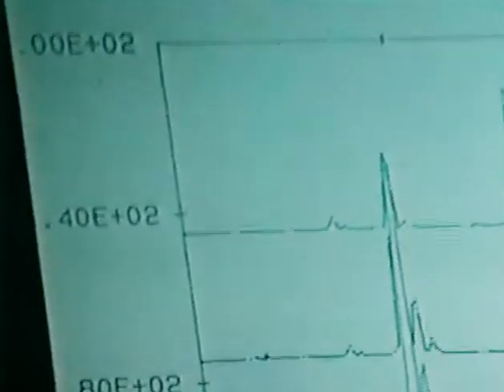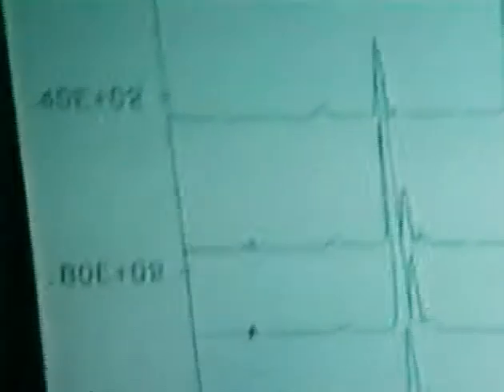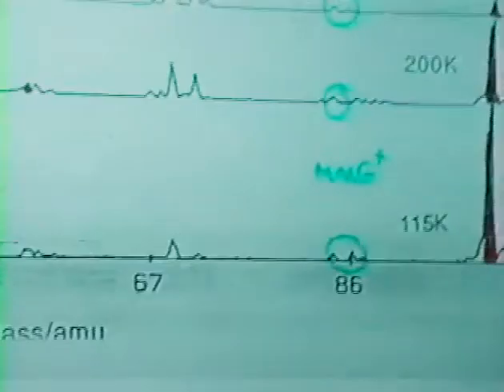Well, a variety of things. This is a very busy slide, and it's a bit too complicated, but it's the kind of complexity that you get if you dose trimethyl gallium on silicon 100 and you do static secondary ion mass spectrometry on it. These panels go from 10 AMU to 100 AMU, and as you come up from the bottom, you're going from low temperatures, 115 Kelvin, up to high temperatures.